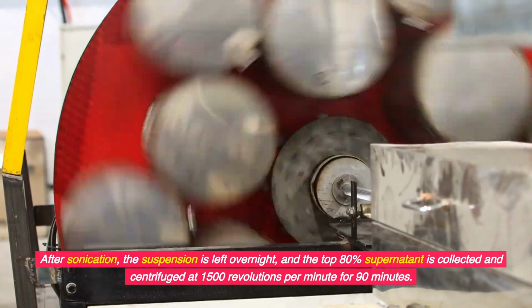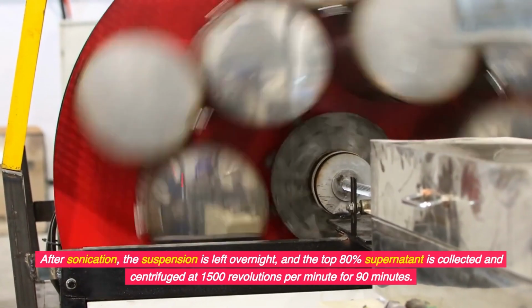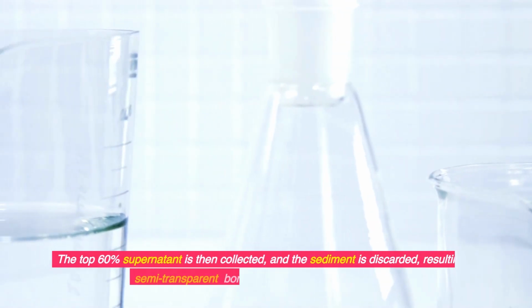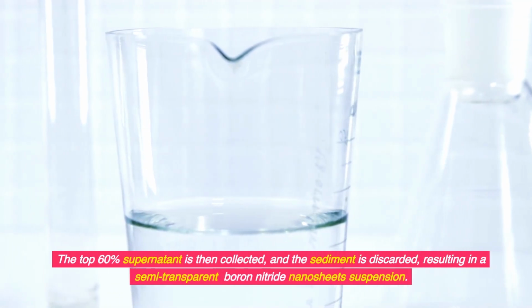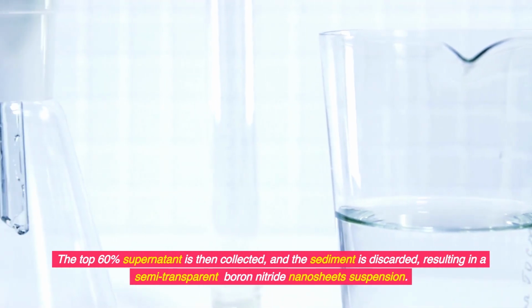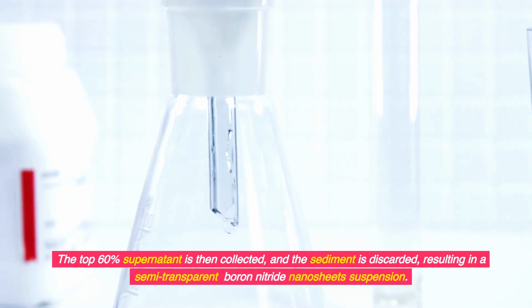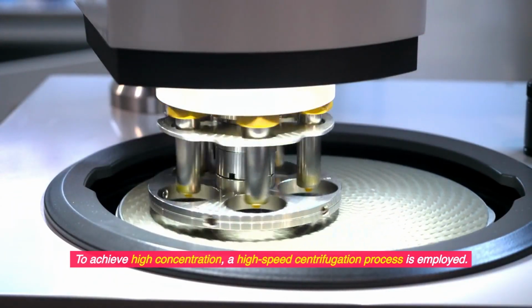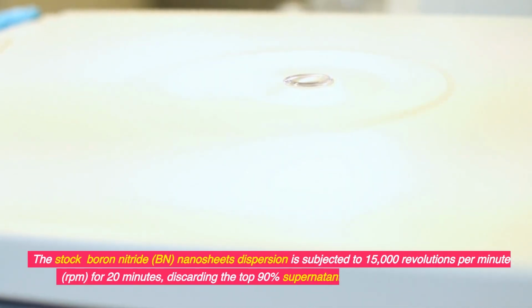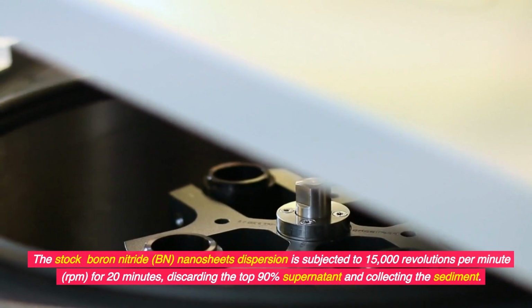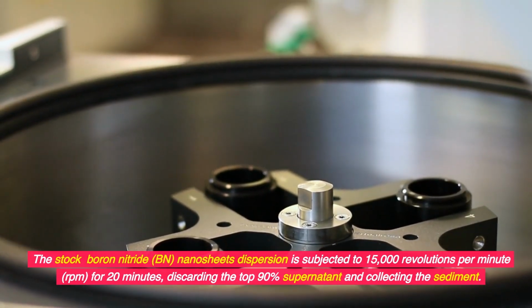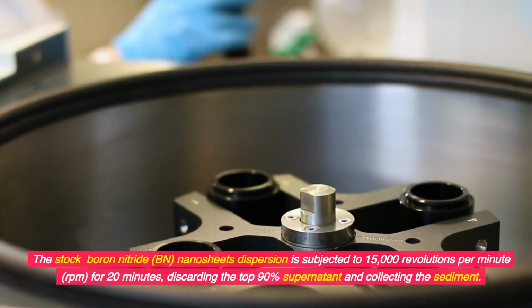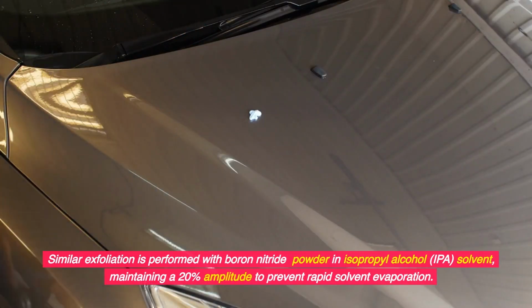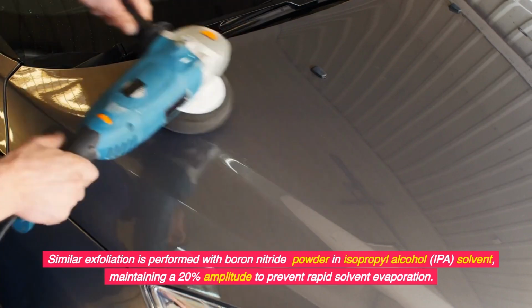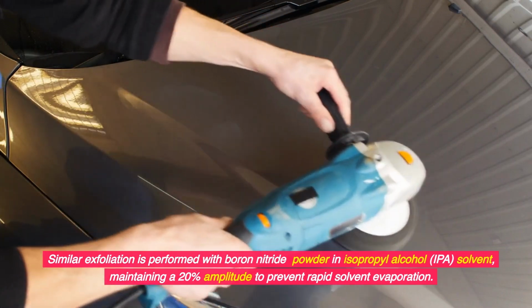After sonication, the suspension is left overnight, and the top 80% supernatant is collected and centrifuged at 1,500 revolutions per minute for 90 minutes. The top 60% supernatant is then collected, and the sediment is discarded, resulting in a semi-transparent boron nitride nanosheet suspension. To achieve high concentration, a high-speed centrifugation process is employed. The stock boron nitride, BN, nanosheets dispersion is subjected to 15,000 revolutions per minute, RPM, for 20 minutes, discarding the top 90% supernatant and collecting the sediment. Similar exfoliation is performed with boron nitride powder in isopropyl alcohol, IPA solvent, maintaining a 20% amplitude to prevent rapid solvent evaporation.